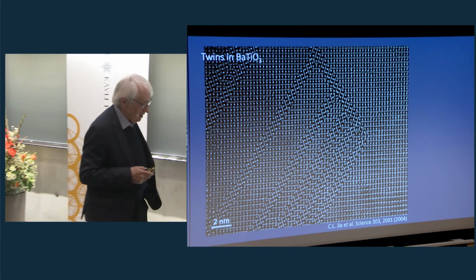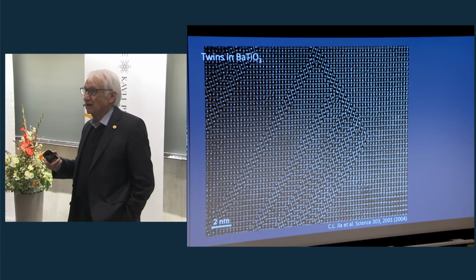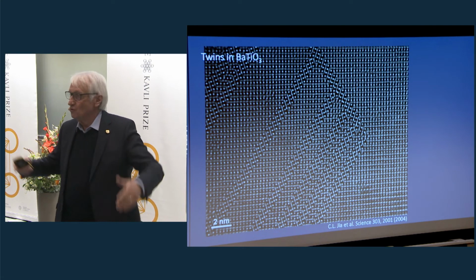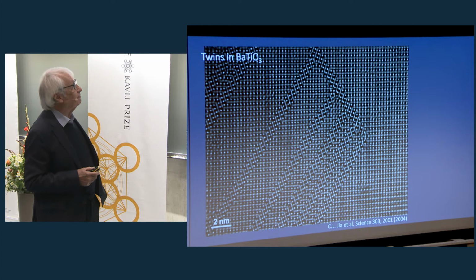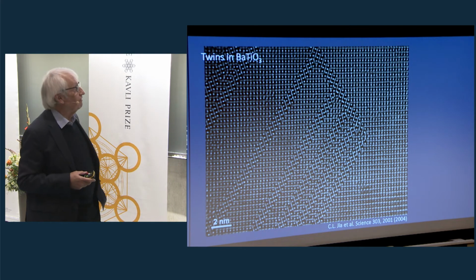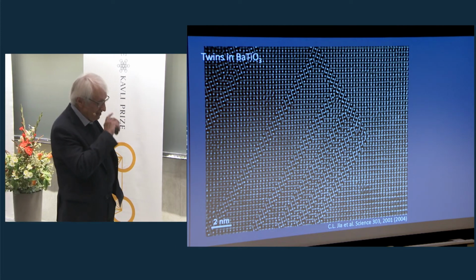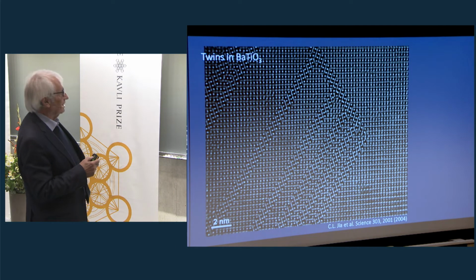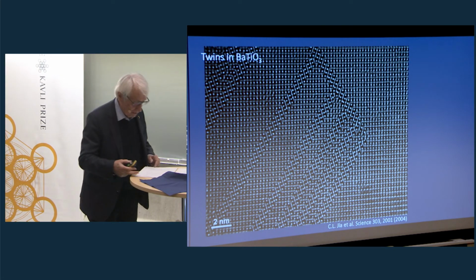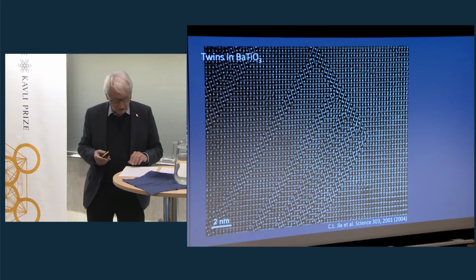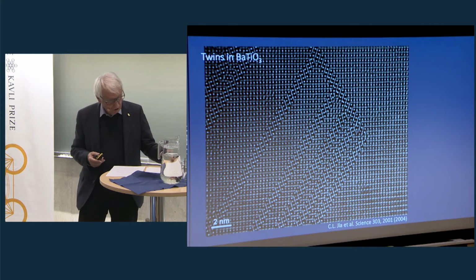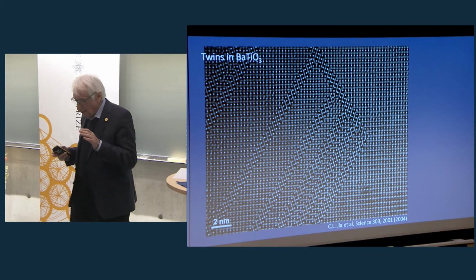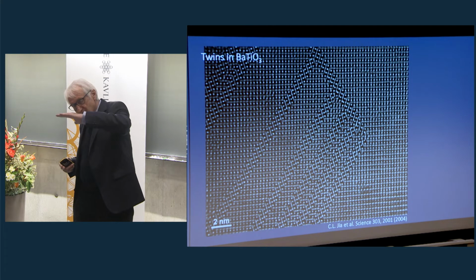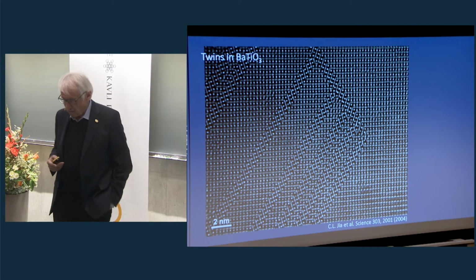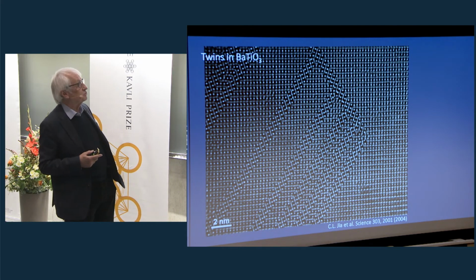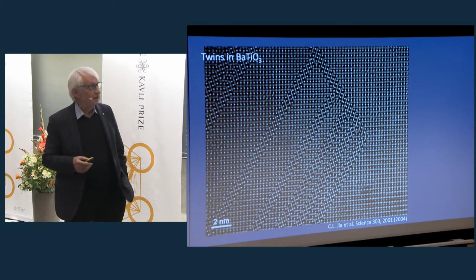The other thing is whether the atomic concentration in a given position is the one you expect theoretically, or the one which you like to have for a particular device function. And one of these cases is barium titanate. Barium titanate is a technical dielectric which is frequently used in technology. And people found out that when they produce these devices from thin layers of barium titanate, the electrical properties were much worse than what they had expected.